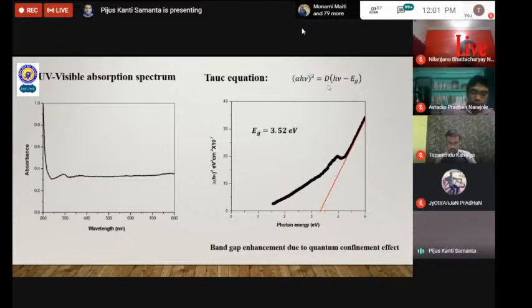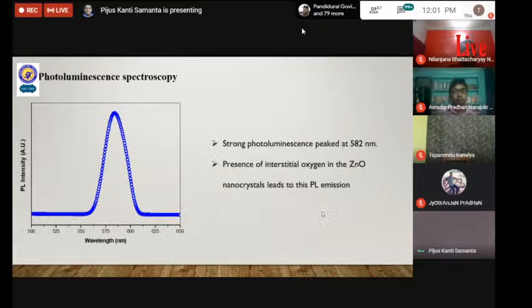And for a direct band gap, this exponent is 2, and for an indirect band gap this will be half. So as you know, zinc oxide is a direct band gap semiconductor. We have used this equation, and getting the slope from the high absorption range, we can calculate the band gap to be around 3.52 electron volt.